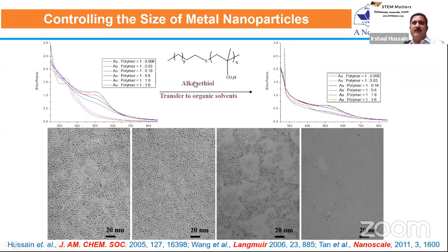Later, we designed molecules which, instead of thiol functional groups, have thioether functional groups. The interaction of this thioether with metal particles is slightly weaker than thiol itself. In this way, we were able to prepare, for example, gold particles ranging in size from 1 nanometer, 2 nanometer, 3 or 4 nanometer, just in one step by controlling the ratio of gold to polymer. When we use a higher concentration of this polymer, we end up with smaller particles, about 1 nanometer. So we were able to prepare gold particles of really uniform size in just one step using these thioether functionalized polymers.